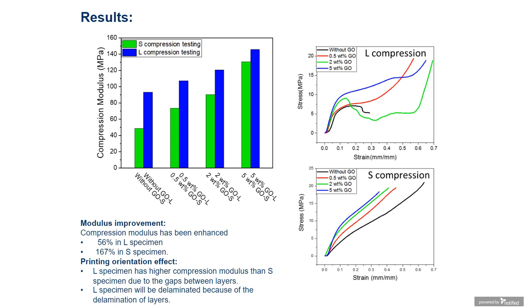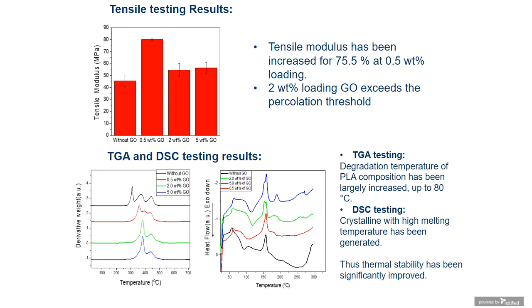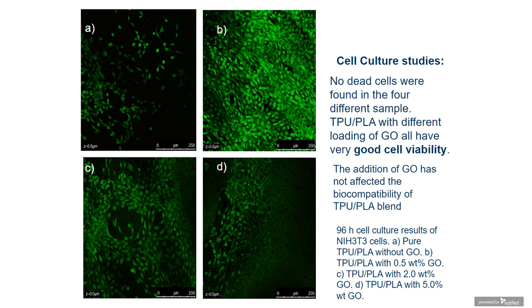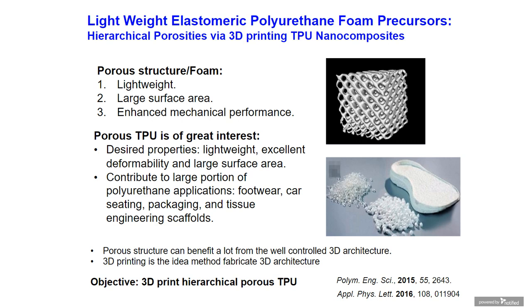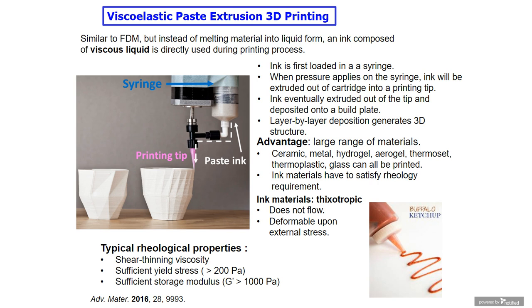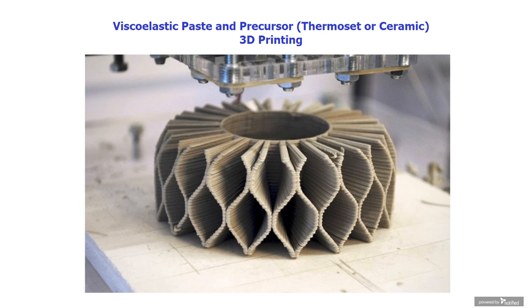where the directionality as well as the presence or the amount of graphene oxide gave us a range of thermomechanical properties. So the bottom line is for nanomaterials and the TPU we used confidently, the addition of as little as 0.5 weight% graphene oxide gave us the best tensile modulus compared to a virgin sample without the graphene oxide. And this is one among the different type of studies that we typically do with nanocomposites. And they are also viable in terms of their biocompatibility. Now, let me skip some of these examples in order to gain more time for coatings.